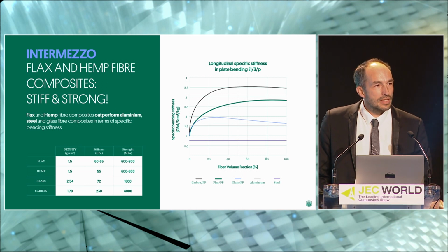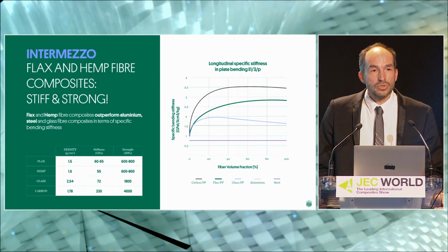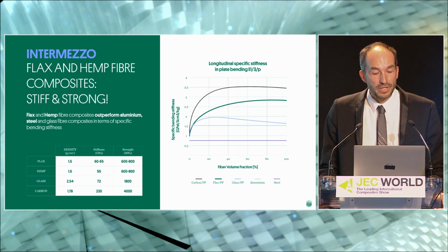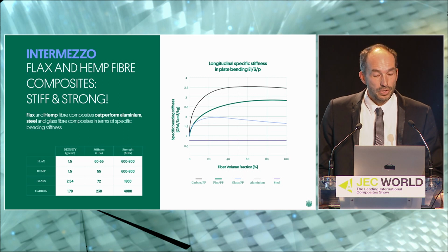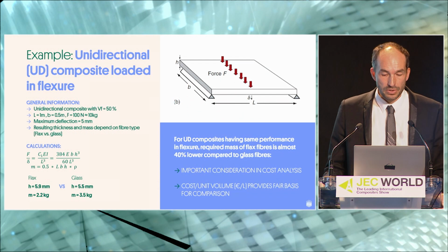So in this intermezzo slide, I would like to emphasize the main strengths and advantages of flax and hemp fibers, and as mentioned just before, the weight of these fibers is an important advantage. They are stiff, strong, but they also have a low weight, with a specific density of approximately 1.5, which is significantly lower than glass fibers. So at the scale of the composite, you can obtain specific bending stiffness, as you can see on the graph on the right part of the slide, that outperform aluminum, steel, and glass fiber composites. So it's really one of the key points of these materials.